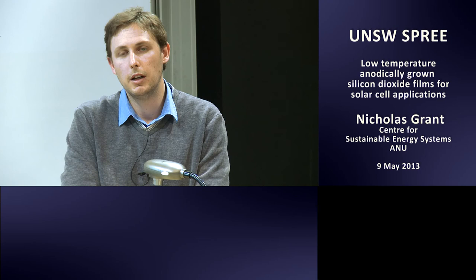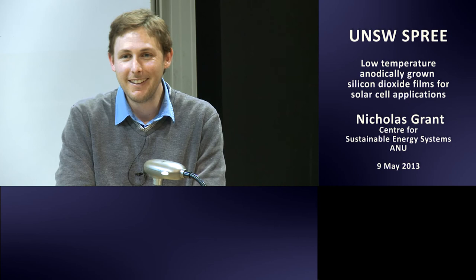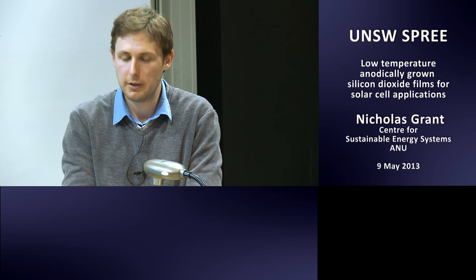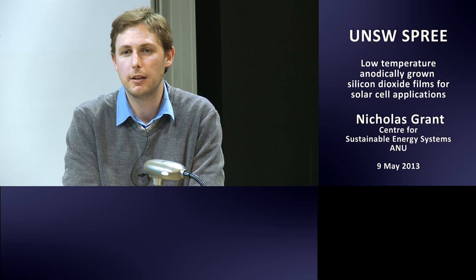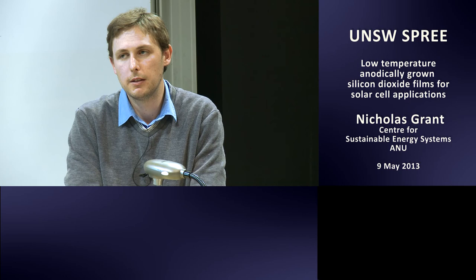Question: Do you have any theories about why the oxides degrade? Answer: Maybe I shouldn't have done a forming gas anneal. Doing a nitrogen anneal instead would tell me whether it's related to silicon-hydrogen bonds. You could show that by simply not doing the forming gas anneal.